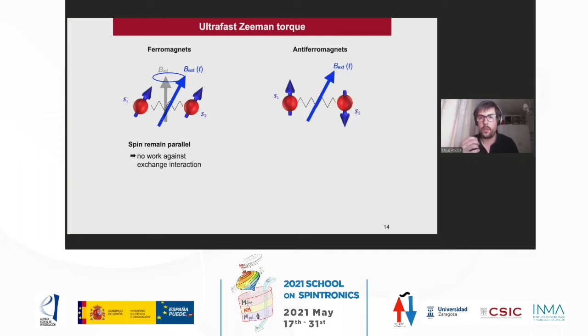In antiferromagnets, if we apply a magnetic field, spin 1 aligns along the external field, but spin 2 should turn and do work against the exchange interaction, so the spins are not anti-parallel anymore. This work against the exchange interaction creates a configuration with larger energy, so larger frequencies.